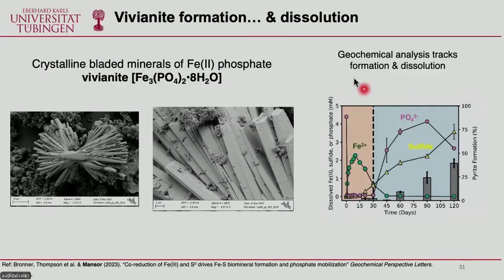This is a really nice figure that Fatih prepared. Essentially, here you see that in the first stage, you have iron being released in the solution as a lot of iron reduction is happening. You also see phosphate decreasing. And then you have vivianite being formed within the first 30 days or so. After that, you get a rise in sulfide and a release of phosphate in the solution, and this is where vivianite is dissolving. At the same time, these gray bars track pyrite formation. So you see that pyrite formation only really starts when you have free sulfide in solution. So we can track vivianite formation and dissolution, but also when the iron sulfide mineral starts to form.